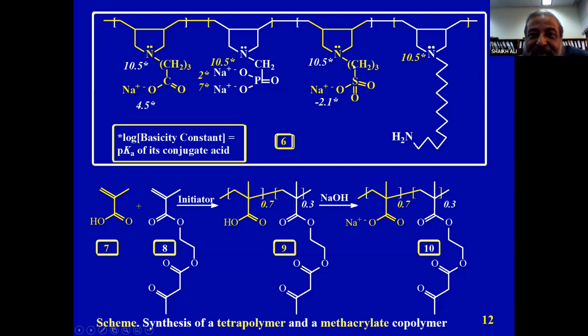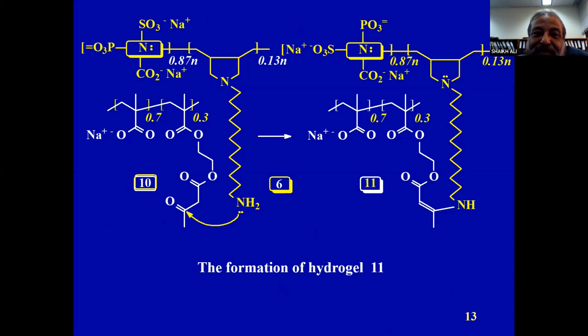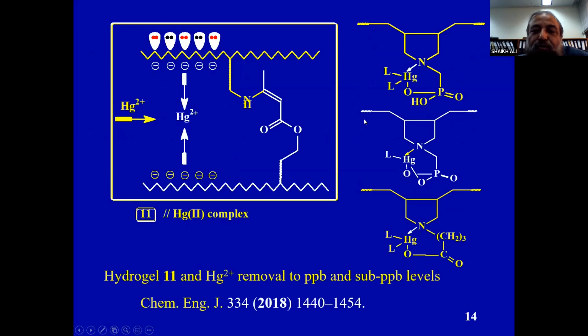monomers to get a polymer whose backbone contains carboxylate, phosphonate, sulfonate, and an amine group. And this amine group can react with this carbonyl to give a cross-linked polymer, and that gives us this cross-linked polymer, and here it is number 11 that contains this cross-link and this CO2 minus, sulfonate, phosphonate, everything is here. Now why do we do that?